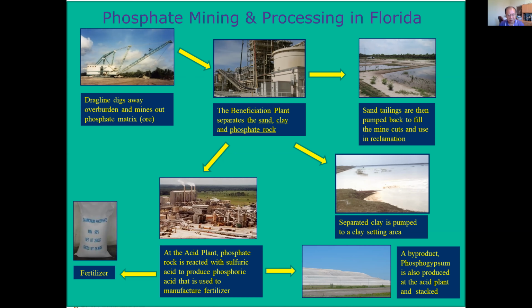So in the acid plant, you generate phosphogypsum, phosphoric acid, and also a phosphoric acid sludge, because during the evaporation process, as the P2O5 concentration increases, lots of the metals like iron, aluminum, rare earth elements precipitate out as a sludge. So this acid is treated currently by a centrifuge. The underflow of the centrifuge product called the phosphoric acid sludge is currently used to make low-grade fertilizer.